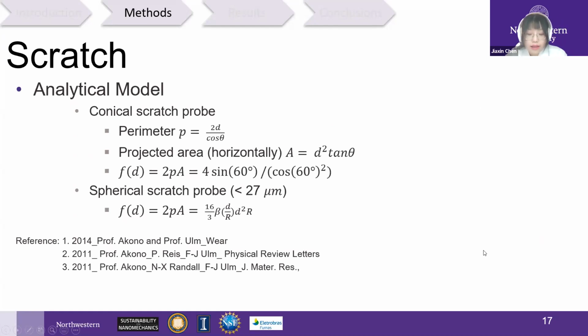In addition, another important element is the probe shape. When the penetration depth, which depends on your force in the experimental setup, is less than the spherical-to-cone transition depth of 27 micrometers, we are in the spherical probe regime. When the penetration depth is bigger than 27 micrometers, we are in the conical zone. In order to have a simpler probe shape and avoid further decoupling, a careful selection of vertical force needs to be considered. This requirement sets the limit for our experimental force range.